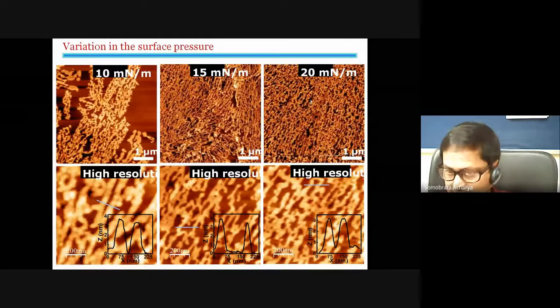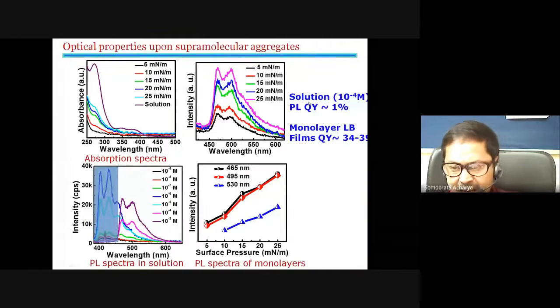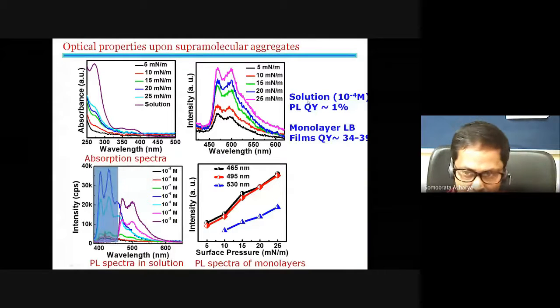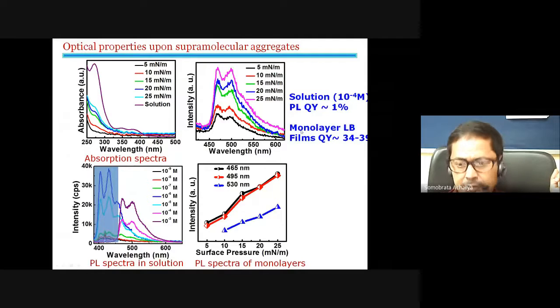But the very interesting thing is that once you increase the surface pressure, you can align them, or you can form different supramolecular assemblies of these molecules, and as a result of that, a jump in the luminescence can happen. For example, this is not luminescent at all in the solution phase. It was giving 1% of photoluminescence quantum yield, but once you take the monolayer LB film, that quantum yield is jumping to 34 to 39% there. So this is a beauty.